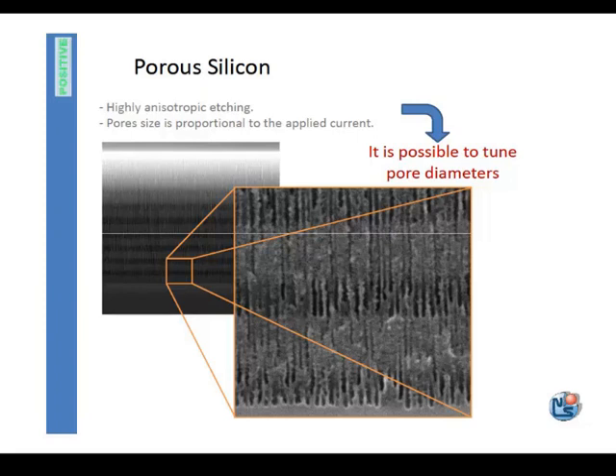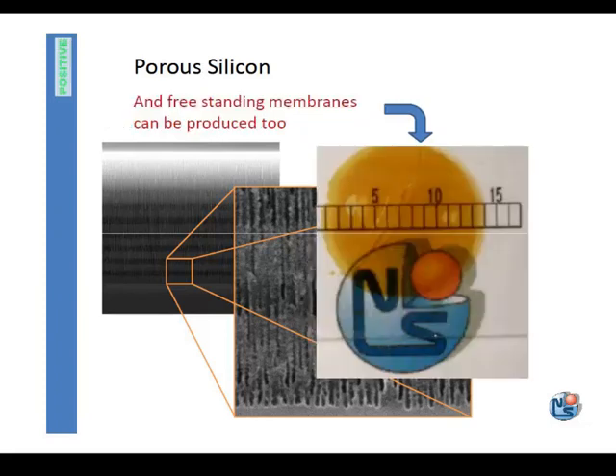quite famous, because you can create this periodic structure with low and high porosity layers. This is a so-called Bragg mirror. It's a dielectric mirror that has very high reflectivity in well-specific wavelength ranges. This is a zoomed image. And if you play with the current during the etching, it is possible to completely detach such a thin membrane and transfer it to some other substrate. This is an image of a very thin membrane. This membrane is only 3 microns thick and nearly 1.5 centimeters wide, and it was transferred onto a microscope glass.